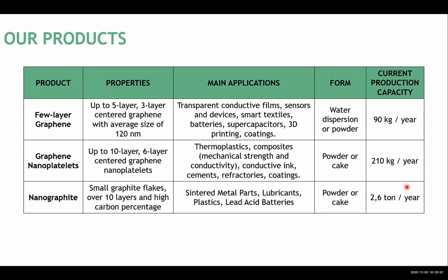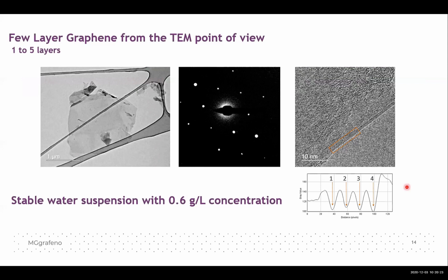So we have all these 3 basic materials, but from these 3 basic materials, you can, in fact, generate another variety of materials depending on the finishing of this product. Okay? So this is the few layer graphene from the TEM point of view. So stable water suspension with 0.6 grams per liter concentration. So of course, this is not statistical about the material, but we do frequently TEM of all the materials to check on number of layers, on crystallinity, and things like that.